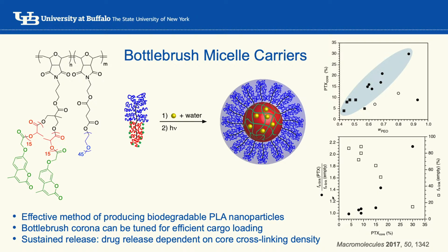But we also use this cross-linking to probe how close these chains are to each other inside the core. So that's the main reason we did it, to try to understand the packing frustrations inside that micelle. So what we've learned from these studies is that, as you make this hydrophilic group bigger and bigger and bigger, so you make the molecule more hydrophilic, it's very counterintuitive. You make it more hydrophilic, so that's this axis. The amount of drug you can load into the micelle actually increases.